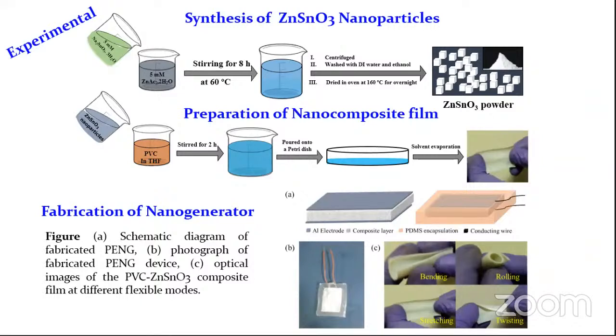For the fabrication of the nanogenerator, we kept the piezoelectric composite in between two aluminum electrodes, a kind of sandwich structure. After attaching the two aluminum electrodes, we connected two copper wires for electrical measurement. After that, we encapsulated the whole device with PDMS to make it mechanically robust so that it cannot be ruptured by any kind of mechanical stimuli. As you can see here, the piezoelectric composite is bendable, rollable, stretchable, and twistable. So we can say that it can easily harvest energy from any kind of motion.